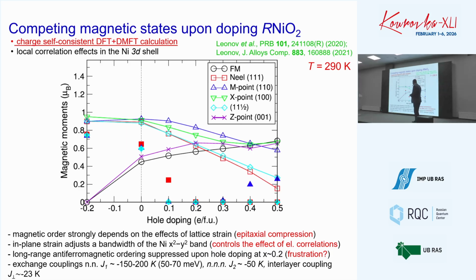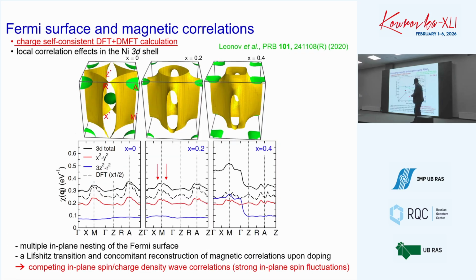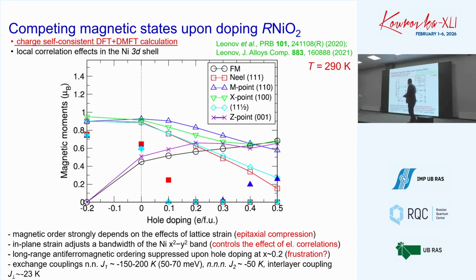And the idea was a bit simple, okay. But for the first time, we focused on this interplay between these two points. We tried to see what our machinery can do for magnetically ordered phases in dynamical mean-field theory. We try to evaluate these two states, they're not that simple, there are many different magnetic states. And on the density functional level, it was some kind of boring. All of them are nearly stable. They compete with each other, but nothing essentially happened upon doping. Although in dynamical mean-field theory calculations, we pump some correlations, some local fluctuations into the system, and these local fluctuations change the Fermi surface and they improve the magnetic state.